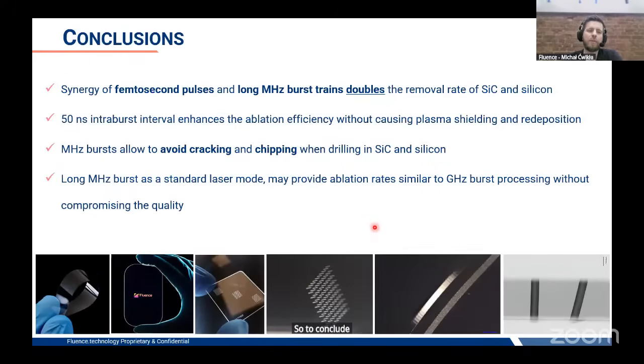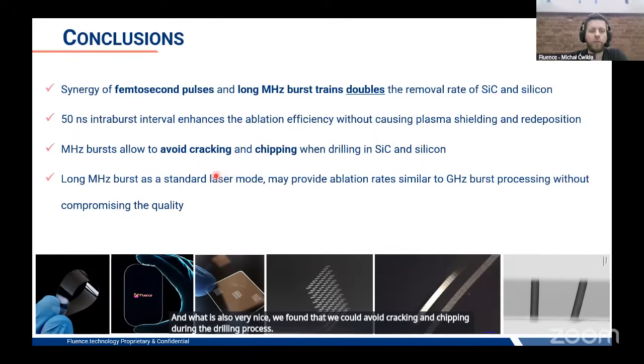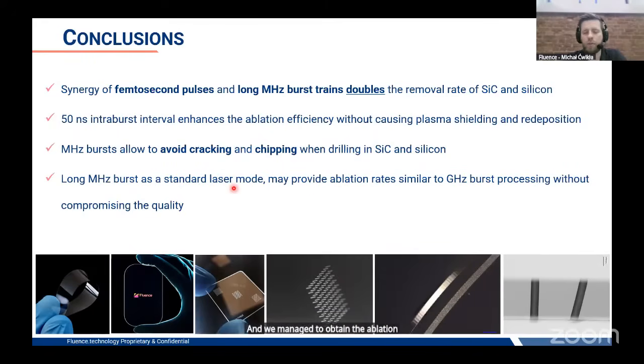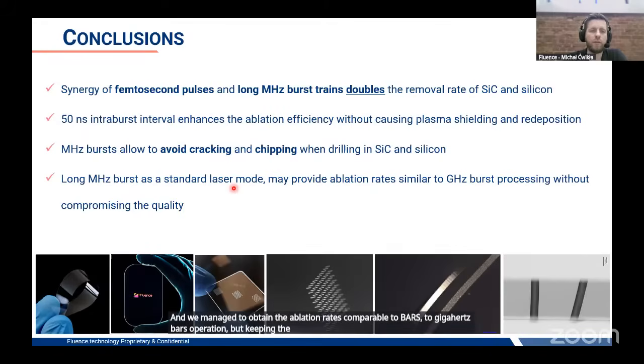So to conclude, during these studies we found that the femtosecond regime works best for processing silicon carbide, compared to picosecond. And also long megahertz burst trains can double the removal rate. The laser burst system is tuned for 50 nanosecond intervals to avoid plasma shielding. And what is also very nice, we found that we could avoid cracking and chipping during the drilling process. And we managed to obtain ablation rates comparable to burst, to gigahertz burst operation, but keeping the quality at the very good level that is usually seen for single pulse operation.